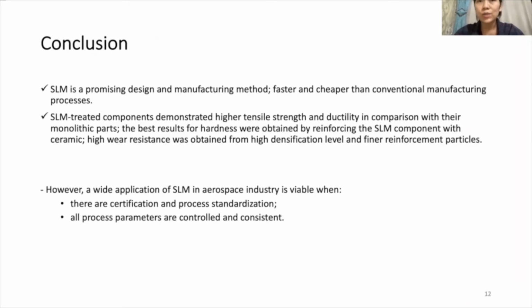According to the studies done, it was found that selective laser melting is a promising design and manufacturing method that can effectively reduce the design constraints imposed by conventional manufacturing methods. Also, selective laser melting has the potential to be faster and cheaper than conventional manufacturing processes while producing lighter components. The fabricated composites, defined in terms of mechanical and structural properties, meet the requirements of higher space components. Mechanical properties of selective laser melting printed parts were analyzed according to previous research studies. The results have shown that selective laser melting treated components demonstrated higher tensile strength and ductility in comparison with their monolithic counterparts, and the best results for hardness were obtained by reinforcing the selective laser melting component with ceramic, and high wear resistance was obtained from high densification level and finer reinforcement particles.